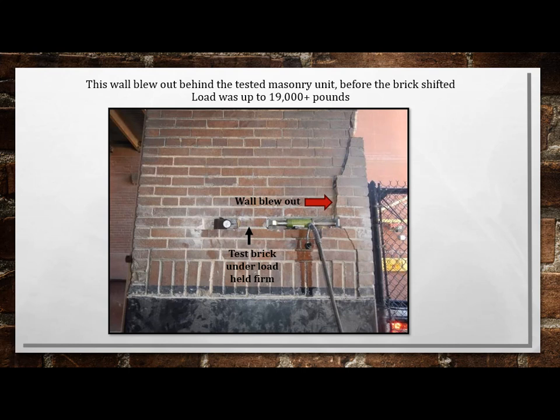But what happened, the back of the wall blew out, because it shows that we should have scooted the test over and done it and had more of a heavier buttress behind it. So this just shows that the shear stress of that center brick was greater than the tensile capacity of the wall. So again, this is a localized destructive test. I kind of figure like I won on this one. So it tore off, masons rebuilt it up. So when you walk by, you can actually see the new masonry in there.